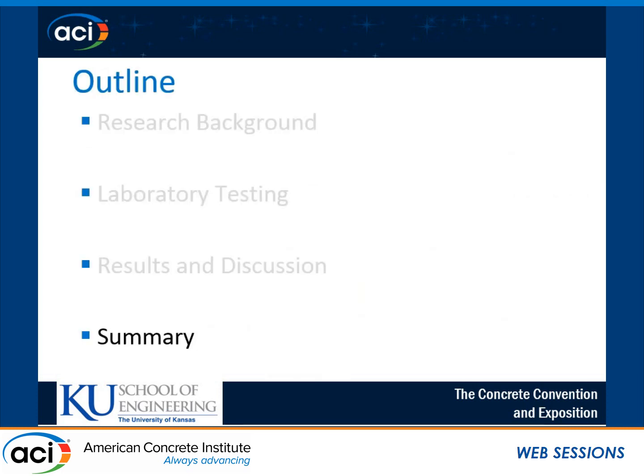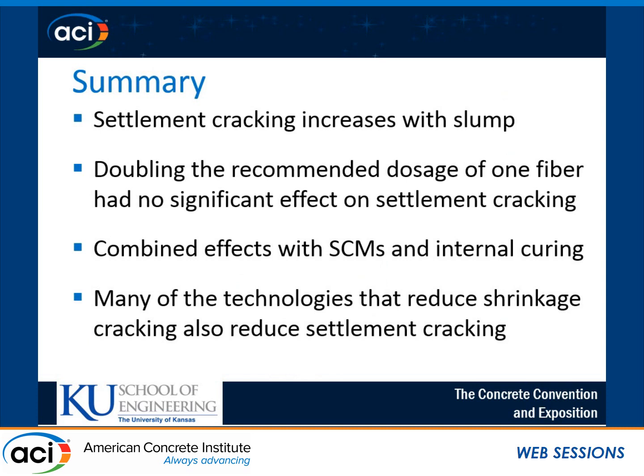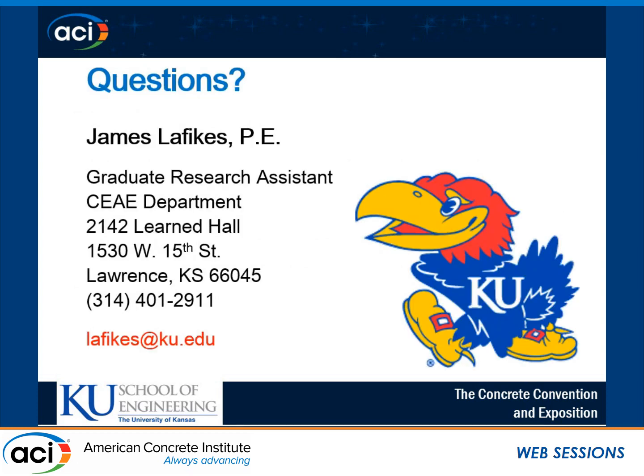And finally, wrapping up, we've shown that settlement cracking does increase with slump, and that for the fiber series that we looked at, the dosage rate doesn't necessarily change the behavior of settlement cracking, at least for the series that we investigated, and that we do have combined effects with SCMs and internal curing. And the most important takeaway for this presentation is that many of the technologies that are available to help reduce shrinkage in concrete mixtures can also reduce settlement cracking. So I'm happy to answer any questions. Thank you.